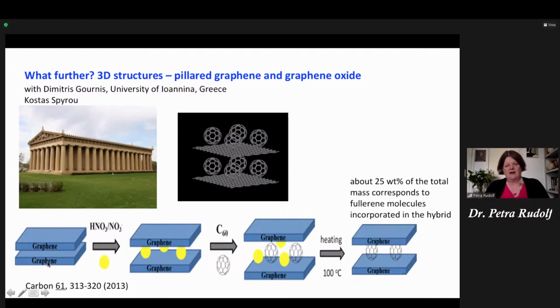He started out with very tiny graphite flakes, so just a few layers of graphene. And then in order to do something like this, I mean, you remember fullerenes are quite big. It's more than 0.5 nanometer across a fullerene molecule. So it does not go in easily. You have to first get the layers apart. And the way you do that is by intercalating nitric acid. And then you expose it to the fullerene, and the fullerene at this point goes in. And the nice thing is that you just have to heat a little bit and the nitric acid goes back out, and you have exactly this structure as we could show.